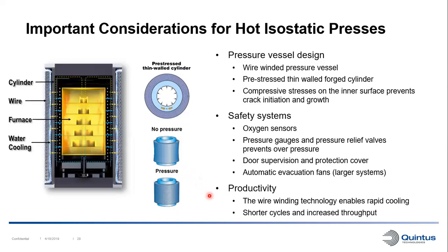And thanks to the wire winding technology of our pressure vessels, we have the possibility to have cooling channels relatively close to the hot zone. So in this schematic picture here, we can see our forged thin cylinder, and then outside of that, we have our wire winding, and then in between, we can have our cooling water. And this effective cooling we have enables us to perform rapid cooling in the HIP system. And the rapid cooling is important because it shortens your lead times, shortens your cycle times for increased productivity that gives you the best process economy.